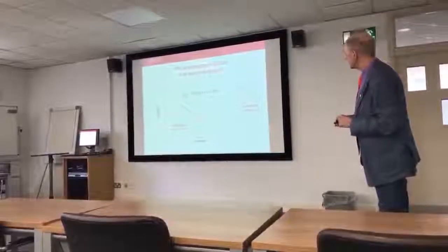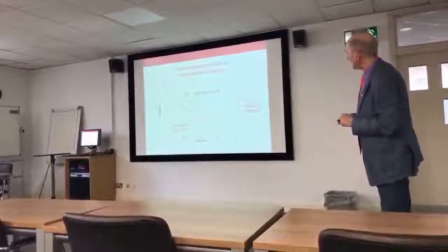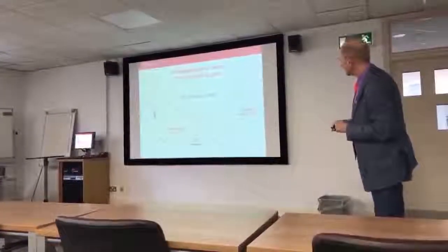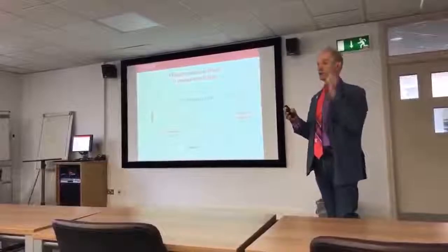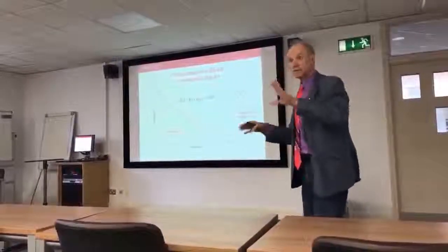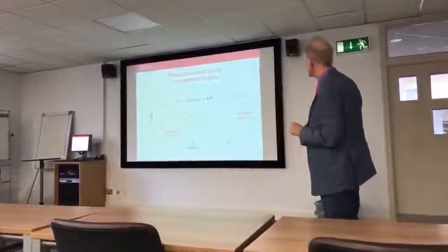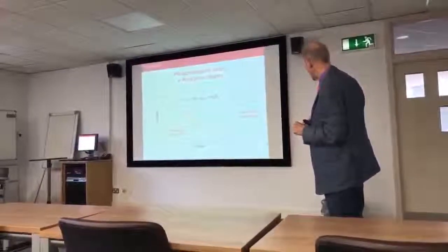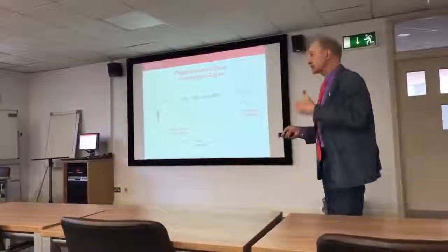We fit the decay to a function which recognizes the fact that it's heterogeneous. This is a log versus time, so the curvature here is a measure of many, many different lifetimes. So it's not a single lifetime, it's a sum of a range of lifetimes. And this stretched exponential allows us to get at it. We fit up to a lifetime and a stretching exponent, and then we can calculate the average lifetime. And that's what we plot here.